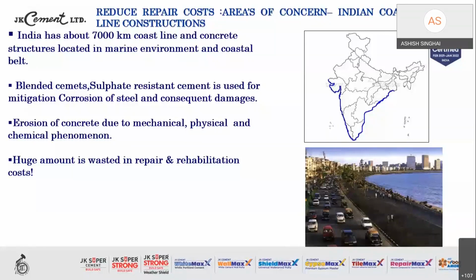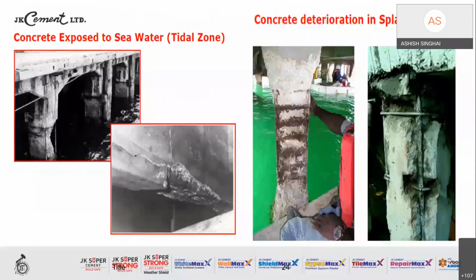That has all come out of our own studies, our own understanding, and the years that we have witnessed the quality of structures which were constructed using all these materials. If ordinary Portland cement is used in the concrete for such coastal area construction, whether it is a pier or any kind of structure situated along the marine lines, you will see what kind of deterioration it can lead to. For concrete exposed to seawater in the tidal zone, the entire embedded steel reinforcement gets rusted and exposed, spalling has taken place, and that particular pier or structure is no longer serviceable. So we can get away with all these things by using the right cement for the right constructions.